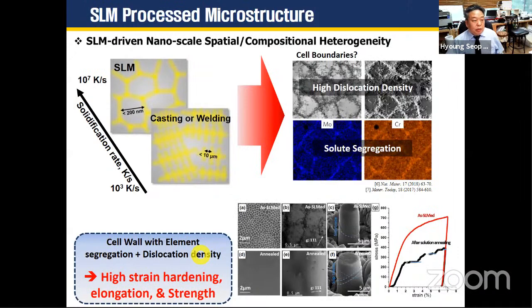And one unique feature of the MAM process materials is nanoscale heterogeneity. It's called cell boundaries and cell structures. It's different from casting structures. Interestingly, cell boundaries are composed of high dislocation density, very high, 1 order of magnitude higher than general casting structures, and very high solute segregation. This cell boundary hinders the dislocation glide very efficiently, but not as strong as grain boundary. And this cell boundary increases the strain hardening, elongation, and strength eventually.